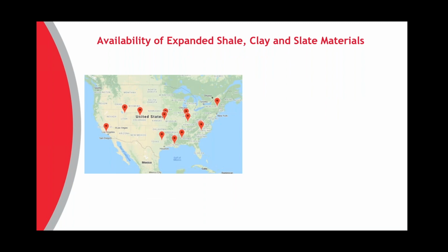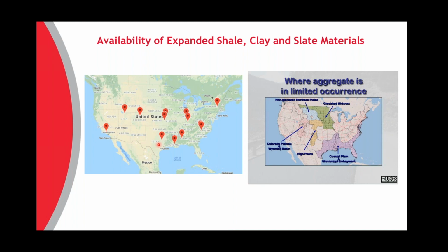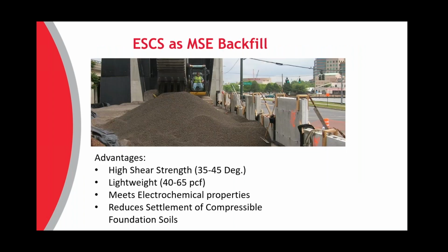Availability of ESCS. Jack showed this illustration earlier about locations. And by coincidence, the locations where this material is available pretty much agrees with the areas where aggregate is limited locally. So, ESCS will be a definite option for you if you happen to be in some of these areas. Okay, so ESCS as an MSE backfill material. Advantages, it's got a very high shear strength. It's lightweight, which can overcome some of your foundation problems if you have those. And it also meets electrochemical properties.